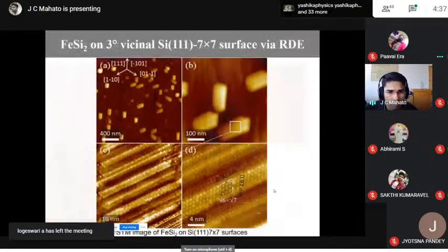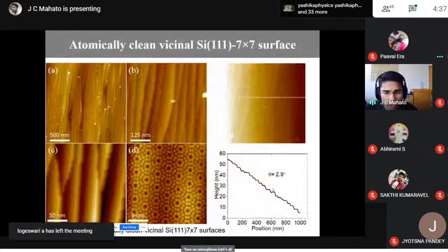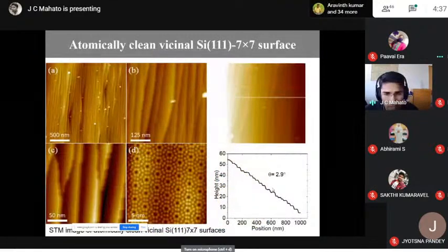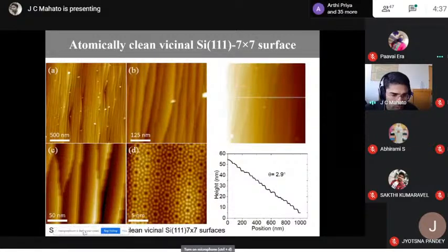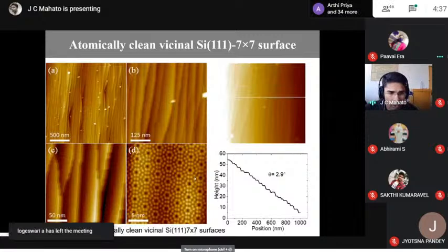So on top of it, we have deposited iron at an elevated substrate temperature, that is 600 degrees Celsius. So when we deposit iron on this atomically clean silicon surface, the iron reacts with the silicon substrate, and it forms iron silicide.